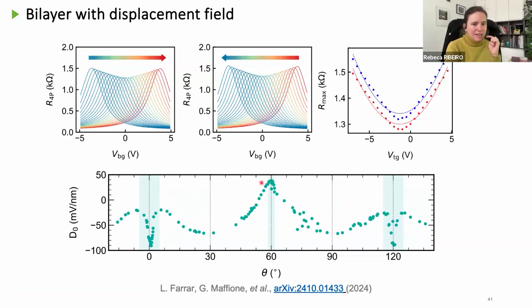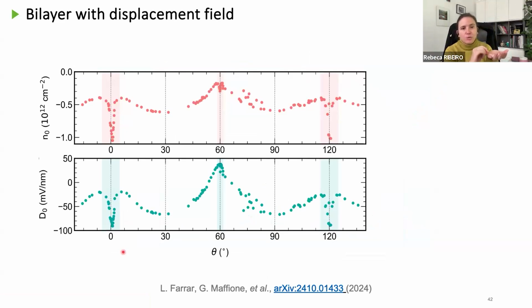Okay, I'm gonna go back in a second to the origin of those dips, but before that I'm gonna tell you that there is something else that is changing in my sample when I do this rotation of the handle. So the intrinsic electric field of the system created by the alignment of the layers is changing, okay? But also the carrier density, the doping of my sample, will change. And they are, of course, changing in the same way because they are strongly related. This intrinsic carrier density is strongly related to the displacement field, okay?